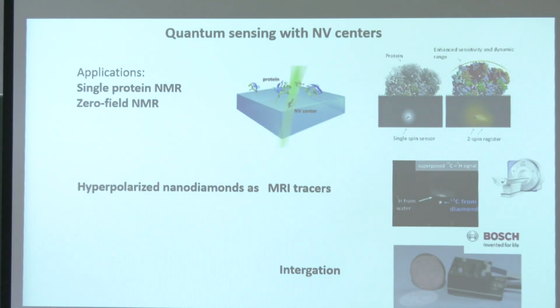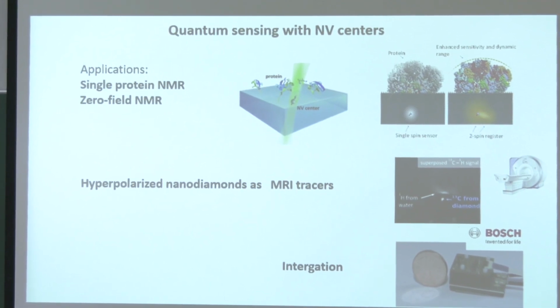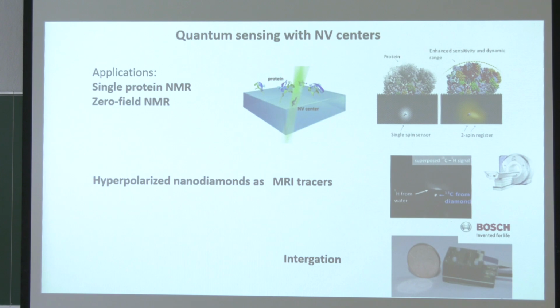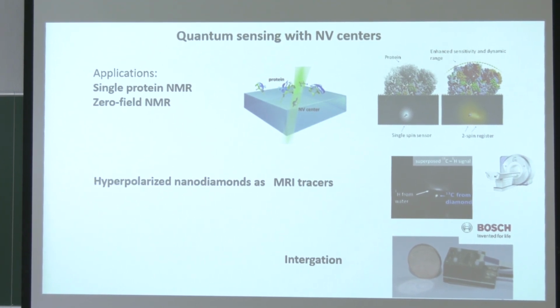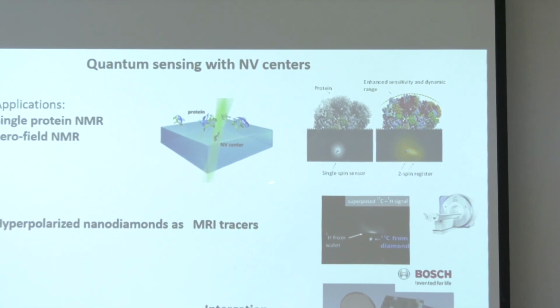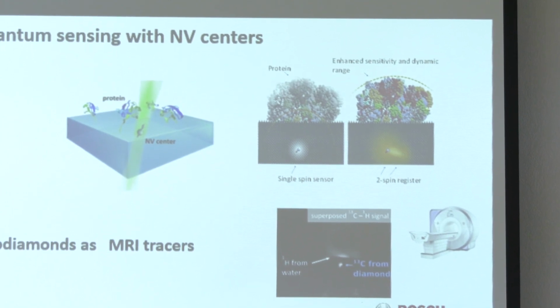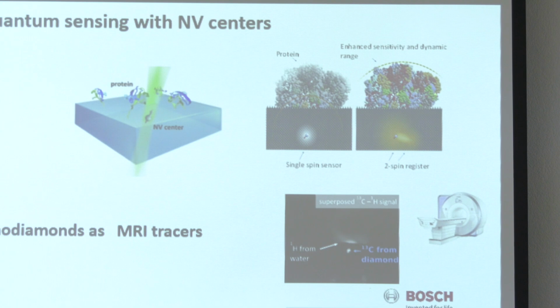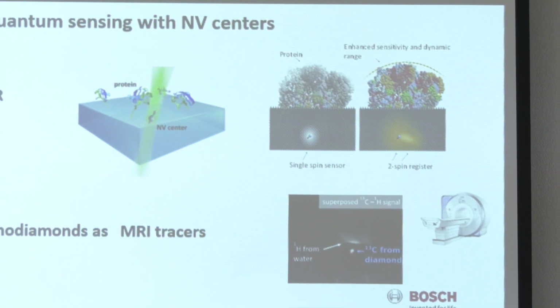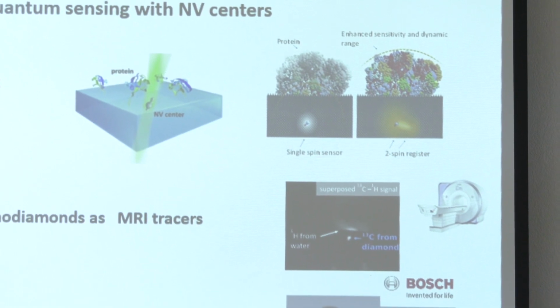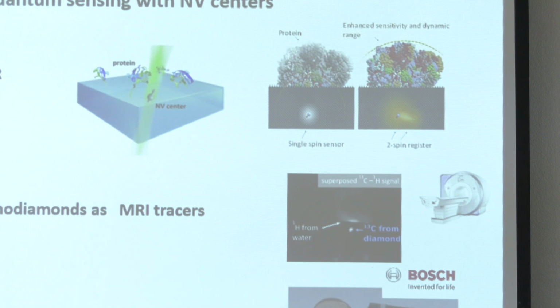All right, I think with this I summarize again, so just a few points that were highlighted today. So now these NV centers are reaching the robustness and controllability to be able to detect very small magnetic field signals associated with NMR, nuclear magnetic resonance, like for example detecting single molecules, but further improvement of spectral resolution and sensitivity is needed. And what was not done so much in the community, but I think is very interesting, is to use actually entanglement, using not a single spin, but a couple of spins as a resource. And you have seen one example where nuclear spin quantum memory was used, but a variety of other scenarios are possible. For example, running quantum error correction on a few qubits here to improve the sensitivity, or use singlet state, which are decoherence protected, but are sensitive to gradients coming from outside.